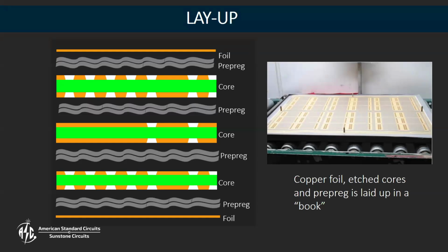Your traveler will have your stack up and basically your requirements for what this layup looks like. So it'll tell you what thickness copper needs to be on the foil layer, what pre-preg layers constitute the space between, like layer 7 and 8 here, for example, which core goes on, how it's oriented, and then you get pre-preg in the next opening, your next core, pre-preg, core, pre-preg, foil. So we'll stack these up as they will show up in the final design that has been designated by the stack up, either that you provided or the standard stack up.